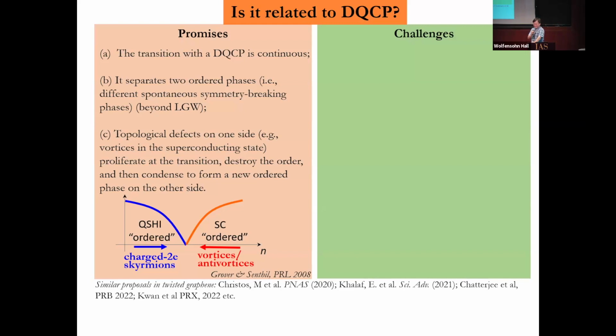It's been more than 1 hour. So I'm going to quickly list what I think is really interesting if we want to think about theory, because I believe there is theory behind this. This so-called deconfined quantum critical point is a continuous transition, which I think experimentally we have something like. It separates two ordered phases that cannot be described by the Landau-Ginzburg theory. In this proposal that I was mentioning, you have a superconducting state, and if you reduce some parameter, for example density or electric field or interaction, the key is to have vortex and anti-vortex, the topological defects, develop in one of the ordered states, and then they condense into a new ordered state.